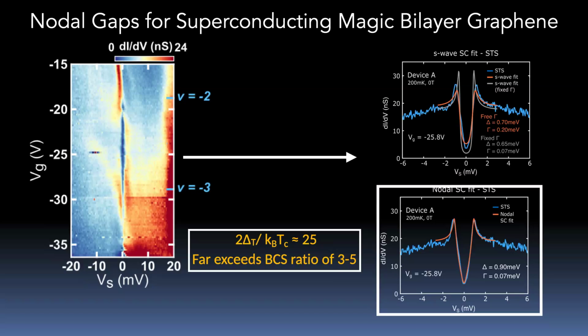Okay, so this is kind of the extent of what we know about the superconductor at this point. It looks like it's nodal. There are some new experiments coming out by other groups that suggest that this is actually true, because they're measuring superfluid density versus temperature, and they're finding behavior that's not consistent with s-wave, it's more consistent with a nodal superconductor. That's pretty much all we know at this point.